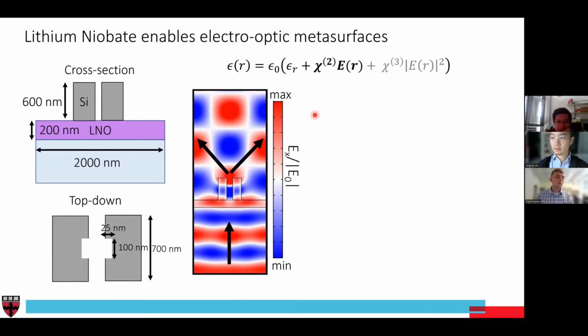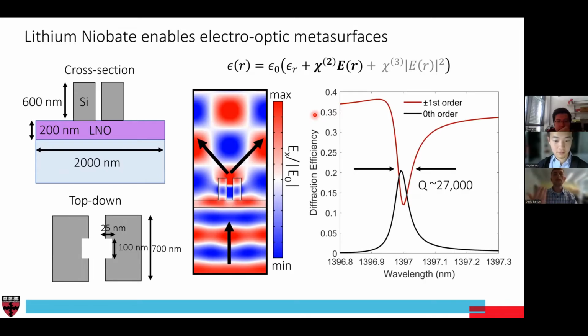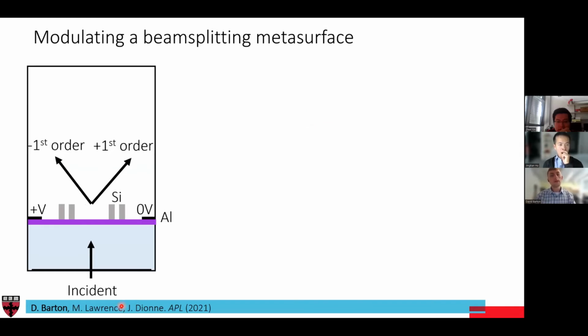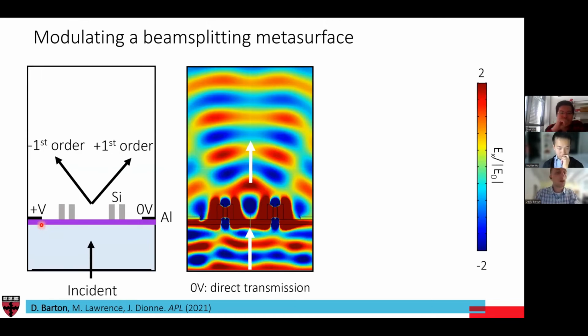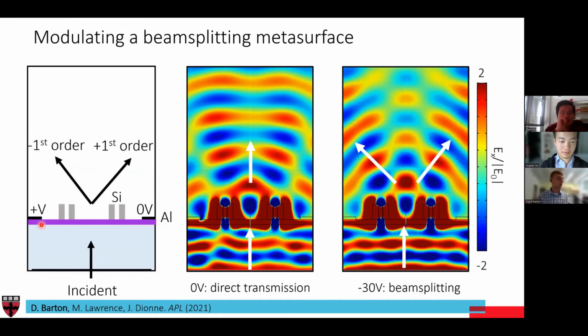especially in tabletop setups, or there's plenty of quantum measurements that you have to do that require beam splitters. And we were also able to engineer in a high Q resonance into this structure. And so we can get very efficient beam splitting and also design these high Q resonances. If we design a structure here where we have a couple of unit cells of this device, we put contacts on the left and the right, we can show that we can change the optical response of this material. So for example, by applying no voltage whatsoever at this wavelength, around 1400 nanometers, we get direct transmission, but by applying a voltage, we can split the light into two propagating directions.